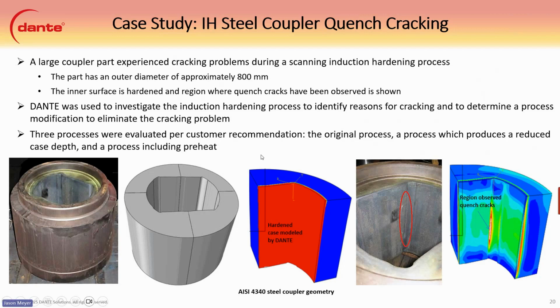DANTE was used to investigate the induction hardening process to identify the reasons for the cracking that they see in the corners here, and then to give a process modification to eliminate the cracking problem. Three processes were evaluated per the customer recommendation. They wanted us to model the original process, or the baseline process, a process which produces a reduced case depth, and then a process that includes a preheat.